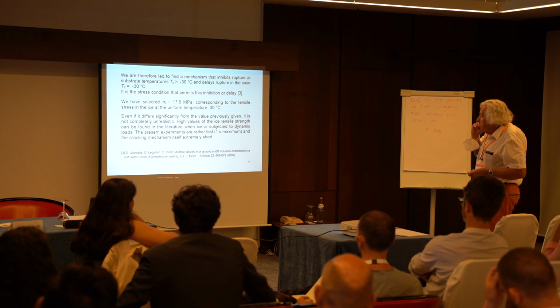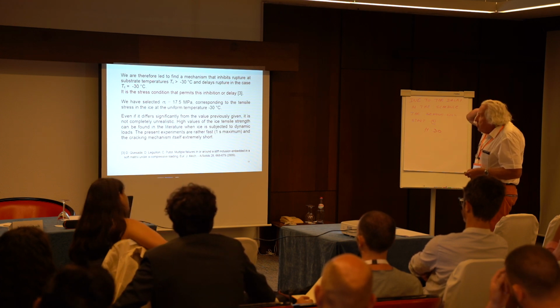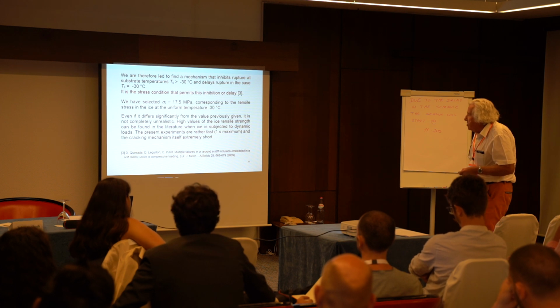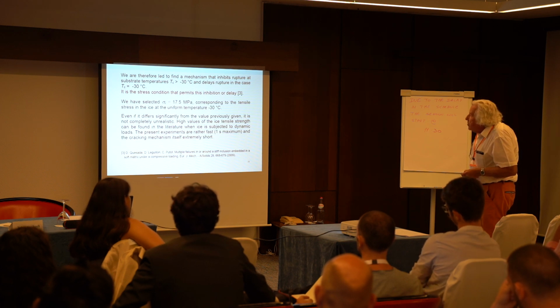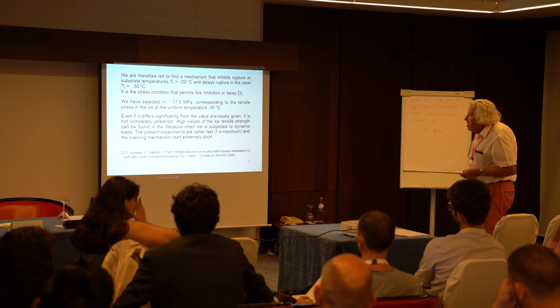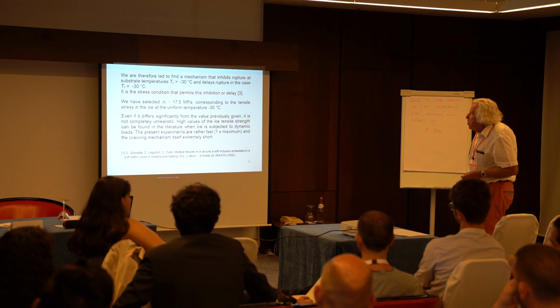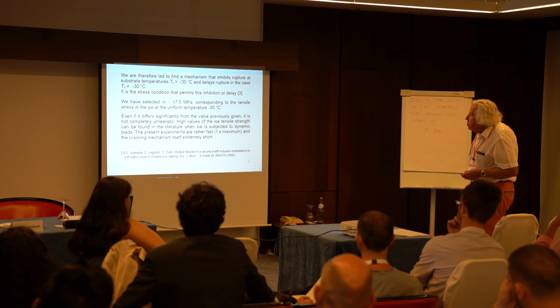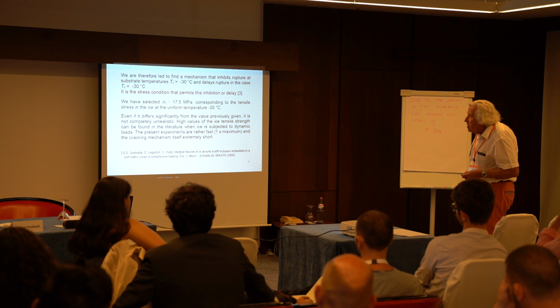We know that it's the stress condition that allows this inhibition, and we have selected sigma c instead of the value 1 proposed in the table. We have selected sigma c equal to this value. This value corresponds to the tensile stress that exists in the ice layer without any crack.